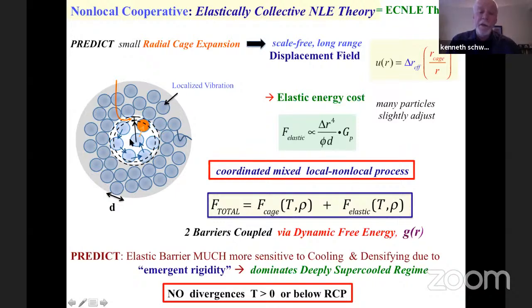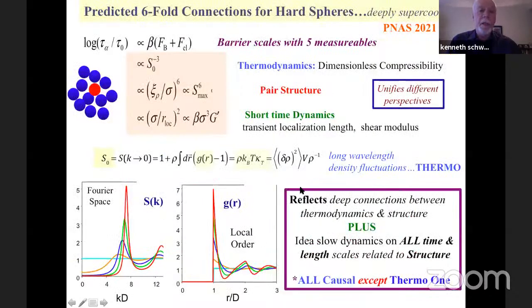When you then apply the theory, it predicts that the elastic barrier is a much more sensitive function of cooling or increasing density, and this is mainly due to the emergent rigidity that's happening in the far field. And this dominates the deeply supercooled regime. The other point to make about this approach is there are no divergences above 0 Kelvin or below random close packing.